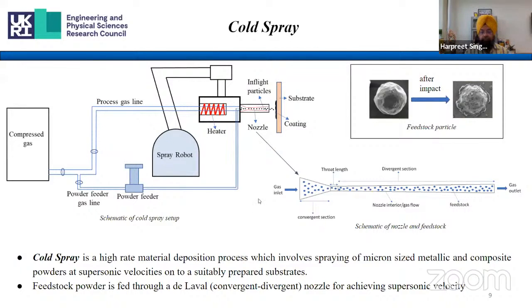Now, when we say cold spray, as I said, temperature is brought to very minimal, but the main driving force to adhere our particles is the velocity here. So that means we have to have something to accelerate our particles to supersonic velocities, and that is where we use this de Laval nozzle, which is a convergent-divergent nozzle. And this is kind of the heart of this whole cold spray system. A lot of studies, a lot of design attempts have been done on this nozzle so that we can achieve these supersonic velocities required for this.